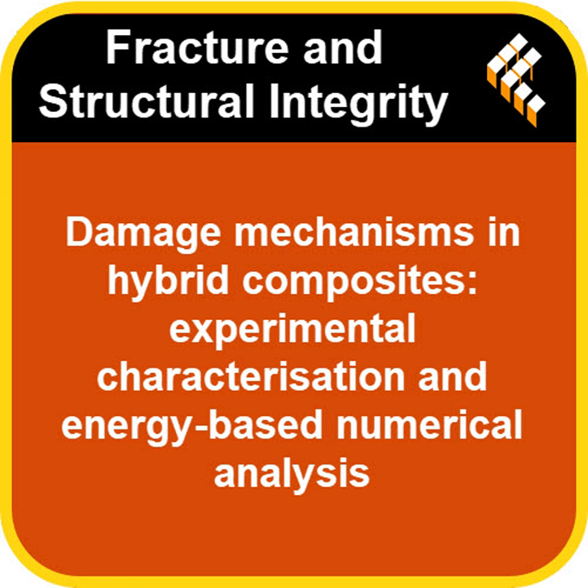What about when the layers start to separate, that delamination we hear about? Right, the peeling apart. For that, they used a surface-based cohesive behavior model, or SBCB. This is specifically designed to simulate when bonded surfaces come apart, like the layers in our composite. It uses a mathematical description, a traction separation model, of how the interface behaves as it's being pulled apart.